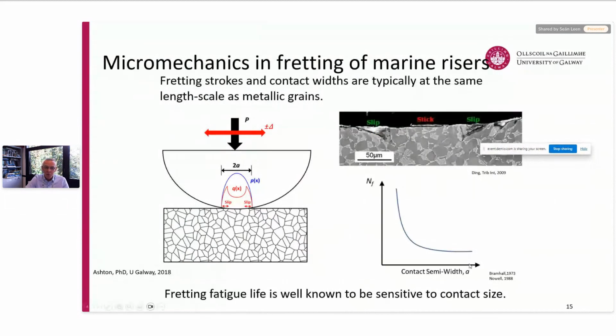And fretting fatigue is well known to be sensitive to contact size. In particular, as the contact size reduces, we tend to find that the fatigue life increases. So we've modified our fatigue crack initiation parameters, and there's a well-known parameter called the Fatemi-Socie parameter, which is quite similar to the Smith-Watson-Topper parameter, and we've applied that in a micromechanical context, as you can see here.